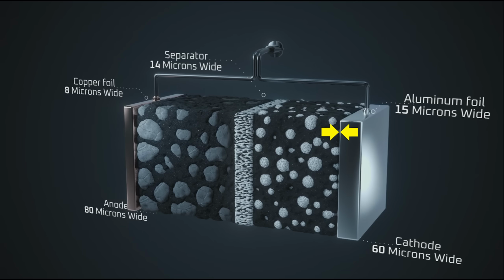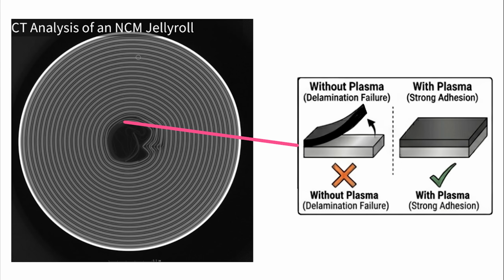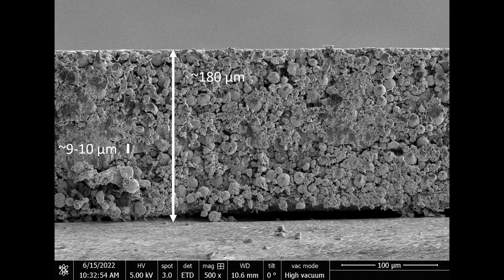Fourth, the plasma treatment might also help the electrode stick more firmly to the current collector. That matters because in cylindrical cells like the 4680, as the spiral gets tighter in the core, the stress at the leading edge of the electrode coating can exceed its bond strength with the current collector and cause it to delaminate. Tesla's dry coating process creates an additional challenge here because it's able to create thicker electrode coatings than a typical wet coating process. Although a thicker electrode coating is desirable because it increases the amount of active energy storing material in the battery cell, it's also stiffer and more resistant to bending, which can increase the likelihood of delamination at the core.